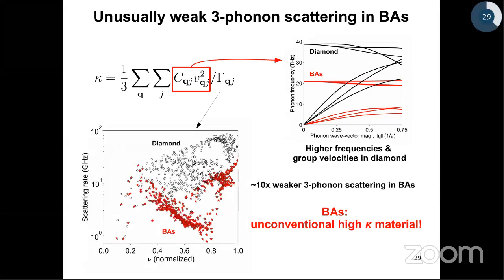But if you look at the denominator, that is the scattering rates, in this case the three-phonon scattering rates, what they found was that the three-phonon scattering rates for boron arsenide was unusually weak, almost 10 times weaker than that of diamond in this small frequency range. So this means that the denominator is smaller for boron arsenide than for diamond. So by having a smaller denominator, boron arsenide compensates for the smaller numerator, and eventually the thermal conductivity of boron arsenide even exceeds that of diamond at room temperature.